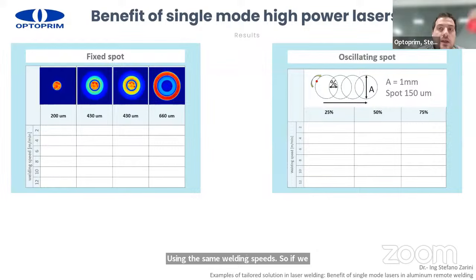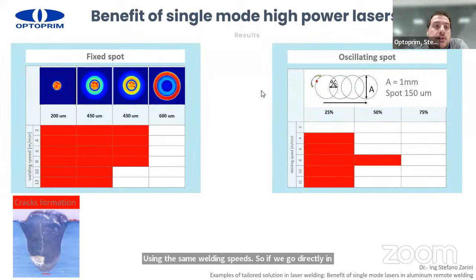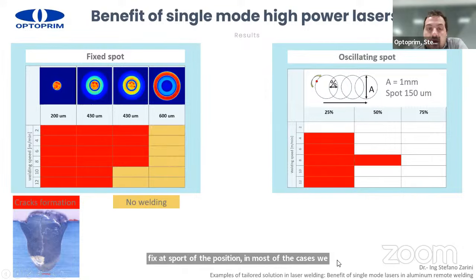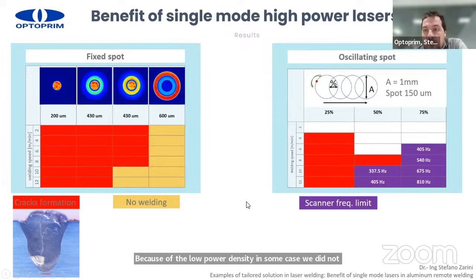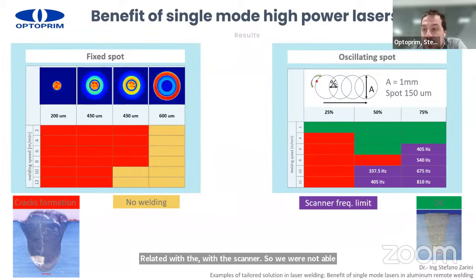So if we go directly in this type of approach, we can clearly say that independently from the energy distribution used with fixed spot deposition, in most of the cases we had crack formations. Because of the low power density, in some cases we did not have any welding. Because of the high scanning speed, so we are going extremely fast, we were not able to achieve super high frequency related with the scanner, so we were not able to cover this area, while finally we were able to obtain nice and smooth welding, crack-free.